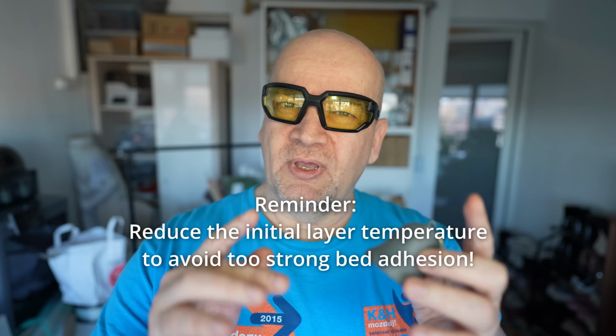Another conclusion. It still sounds like a metal, but not like the carbon fiber version. Thank you for watching. Just kidding. I really like its mechanical properties too. Great layer adhesion, and it is even tougher compared to the carbon fiber version. Don't forget it requires higher print temperatures, and very easily you can ruin that layer adhesion. With a little bit lower temperature, faster printing and similar, the layer adhesion may be weaker, so pay attention to this.